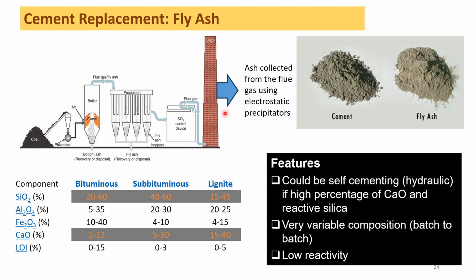Now, in the thermal power plant, when I burn coal, what is left behind is the ash, and the ash that I collect from the stack, the flue gas, is this fly ash, and it's a grayish looking material. The issue is that coal varies significantly from the source, and even from the same source batch to batch, so we get a very large variation in the fly ash properties. Now, the fly ash itself could be self-cementing. That is, it could be hydraulic: I can simply add water to it and it starts setting and gaining strength, if I have a high percentage of calcium, so that is a class C fly ash.